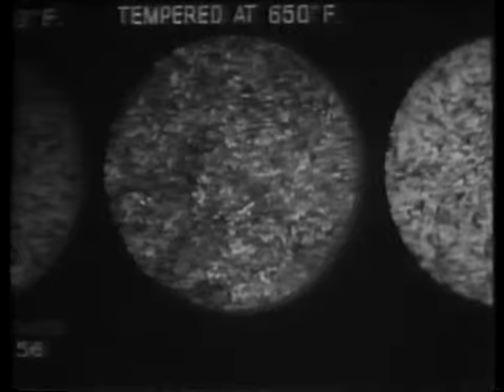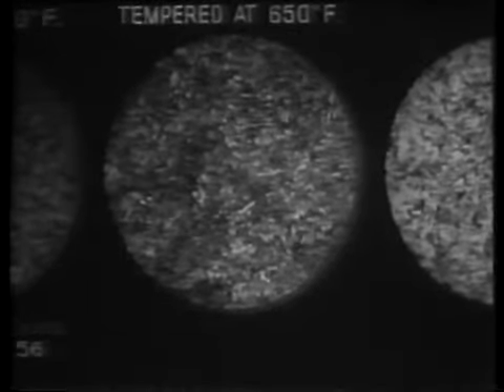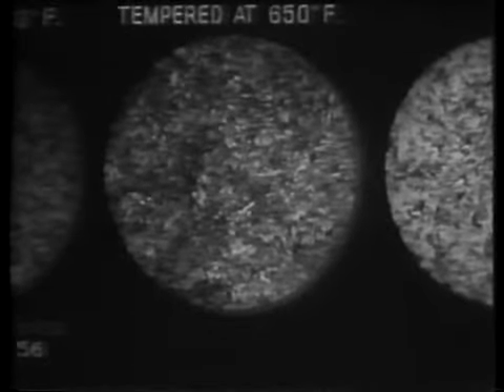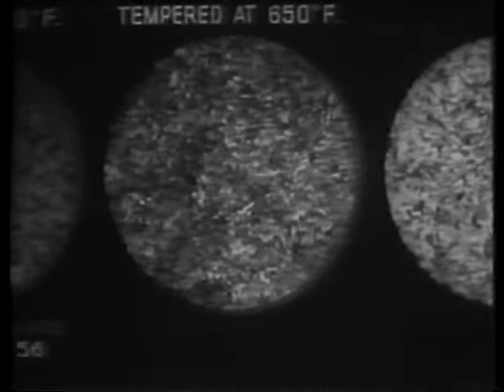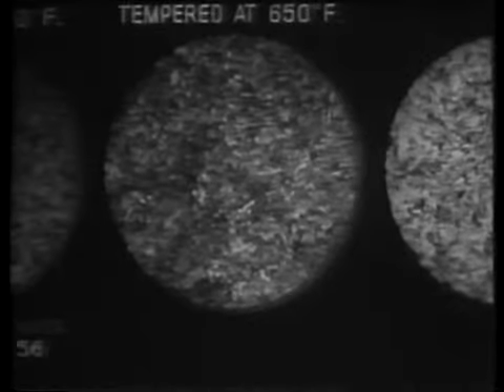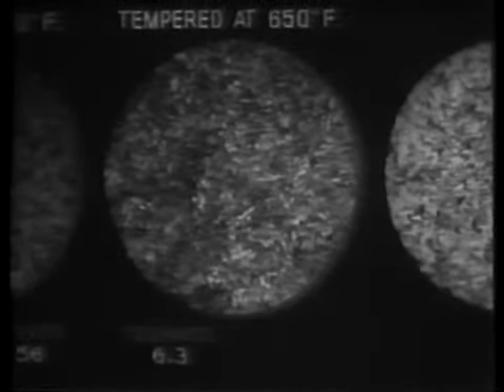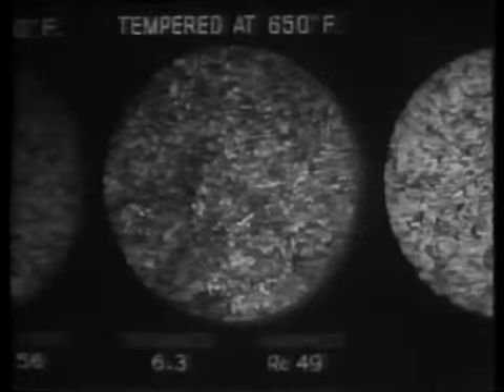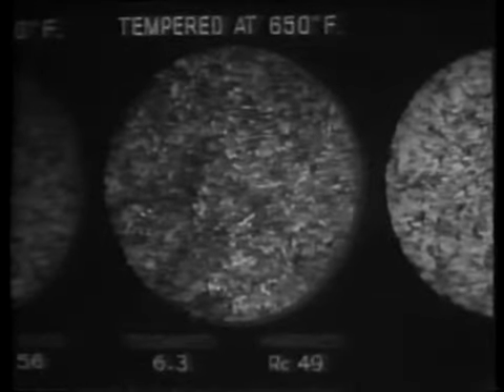When the steel has been tempered at a higher temperature, 650 degrees, a recognizable change can be seen in the structure. The carbide has started to precipitate from the martensite. The carbide appears black in the micrograph. The toughness, however, has barely changed. It is now at 6.3, even though the hardness has decreased to 49. It is necessary to go to higher temperatures to obtain marked toughening.